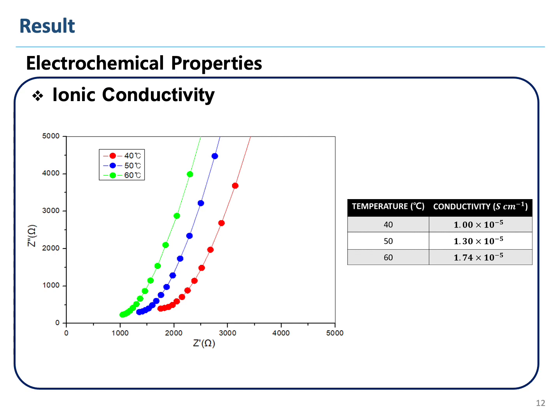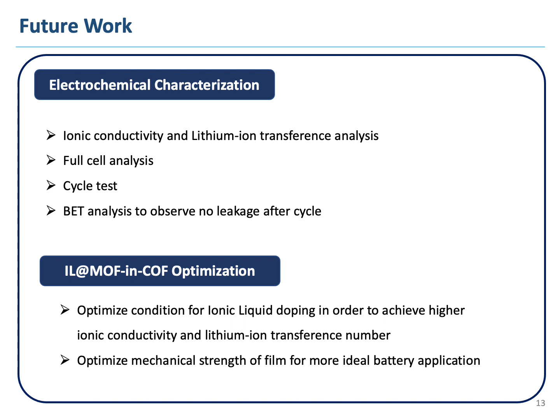Next is the electrochemical properties. From this, we can know that the ionic conductivity of this composite electrolyte increases with temperature, and at 60 degrees Celsius, it can achieve an ionic conductivity of 1.74 times 10 to the power of negative 5 Siemens per centimeter. For the future work, we will continue with the electrochemical characterization, which is the ionic conductivity and lithium ion transference analysis, full cell analysis, cycle test, and also BET analysis to observe no leakage after cycle.